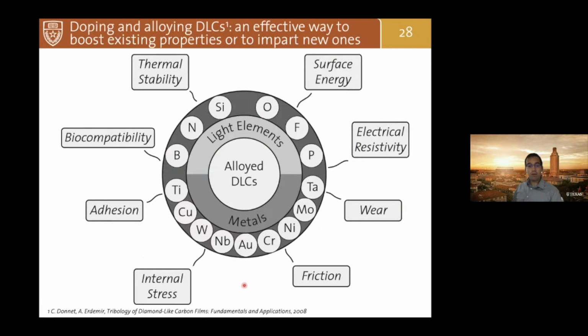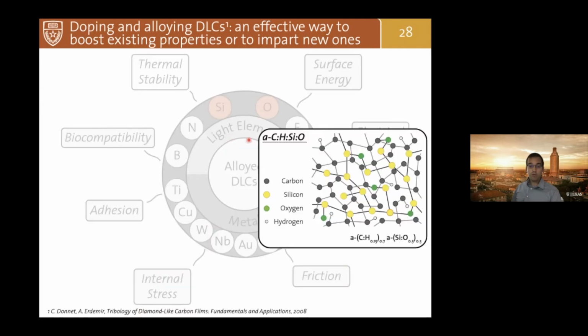So as in the semiconductor industry, if you introduce new elements, you can actually tune and tailor the properties of diamond-like carbon materials. So here you see a lot of work that has been done in the last 20 years. And today, what I'm going to focus on is the effect of silicon and oxygen, because silicon and oxygen have been shown to increase the thermal stability, but the origin behind it was not established. So that's why we started looking at this DLC that includes silicon and oxygen atoms.